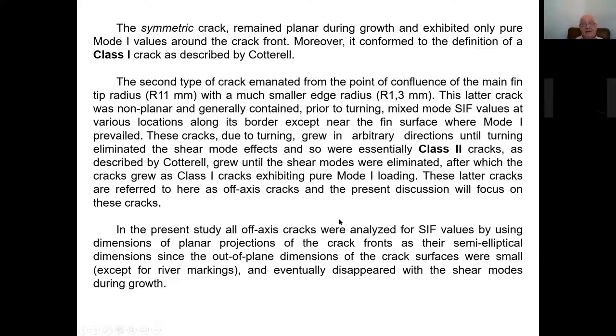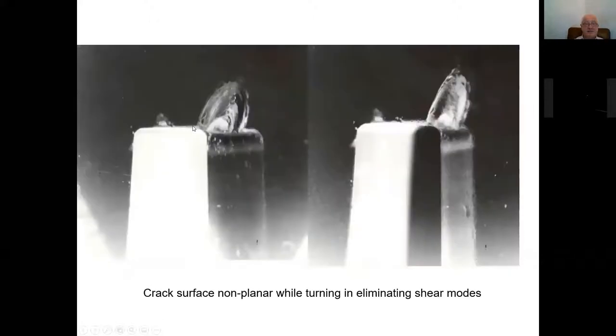And on the other hand, we may have class two cracks, which grow eliminating shear modes. They move towards class one, but it depends on the moment in which you are stopping the test. You can still have mode two situations. So shortly speaking, as we are going to see, we are going to have all kinds of crack surfaces, but mainly all cracks will get towards symmetric cracks.